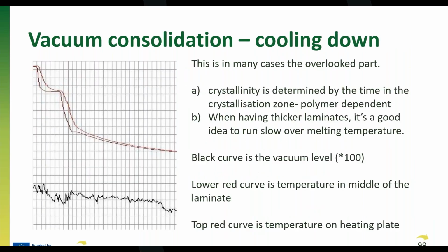And then the cooling down. This is in many cases the overlooked part of the process, because here's actually where you determine the properties of your laminate afterwards. Because crystallinity is determined by the time you are in the crystallization zone, and this is dependent on the polymer, of course, where that is. But you have to take time enough, or not take time enough if you want to have crystallized or not crystallized materials when you are finished.